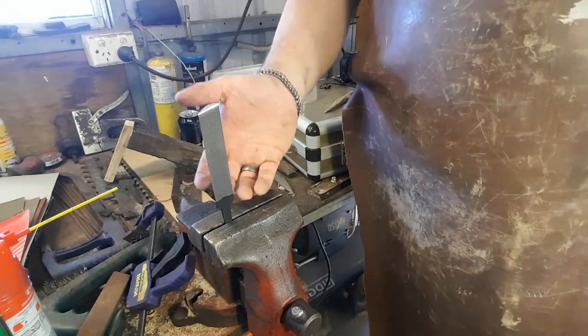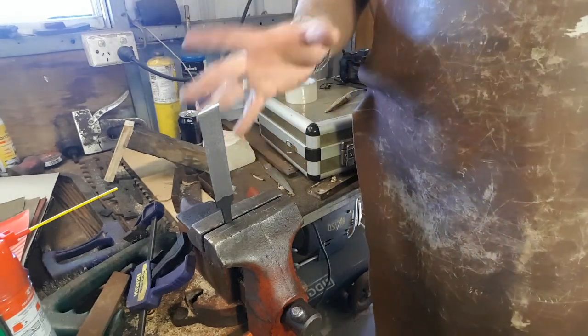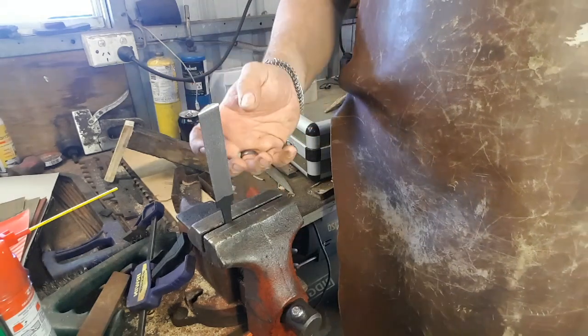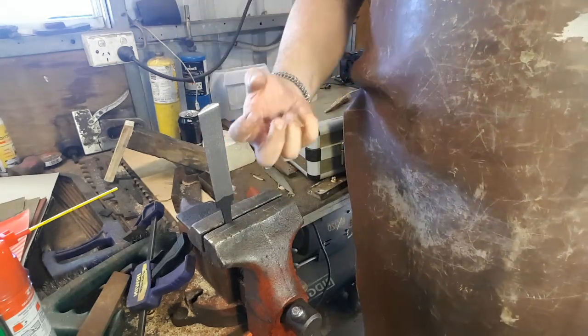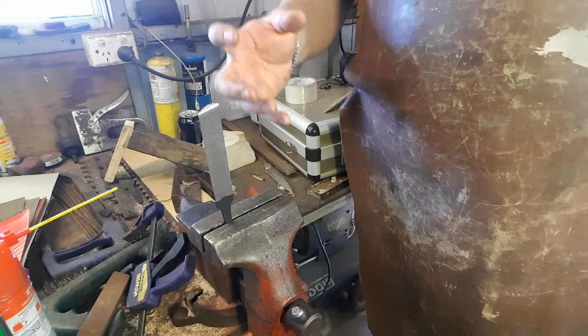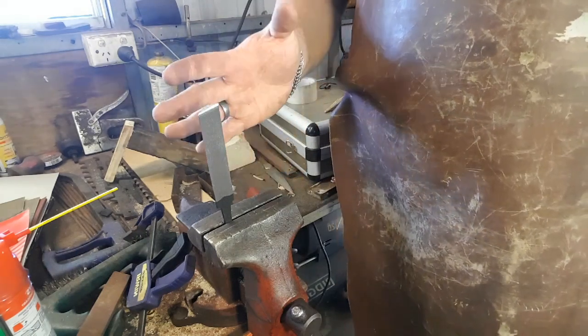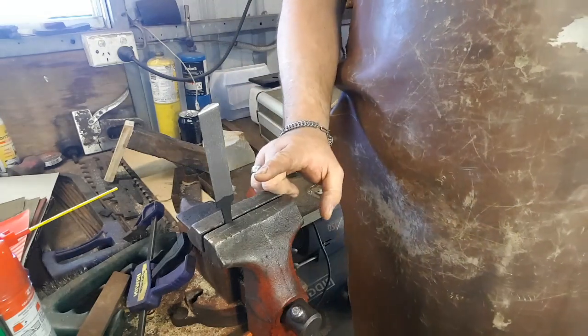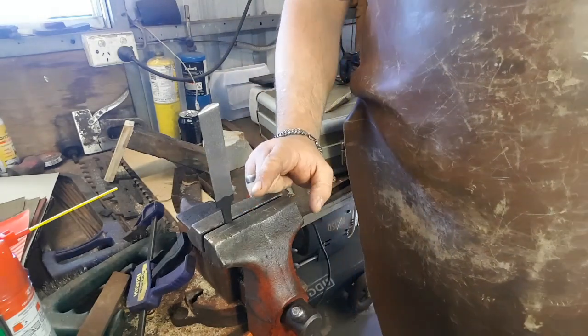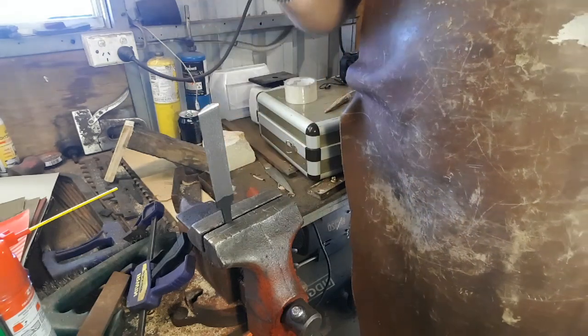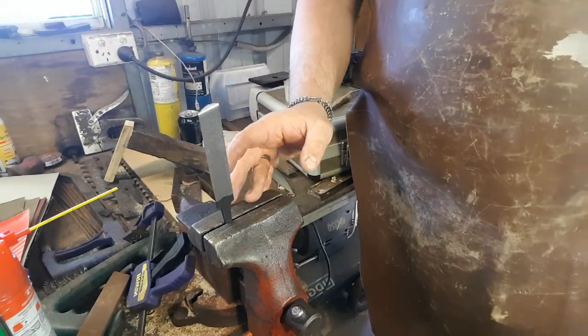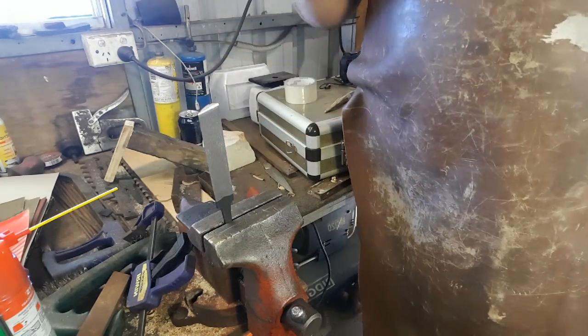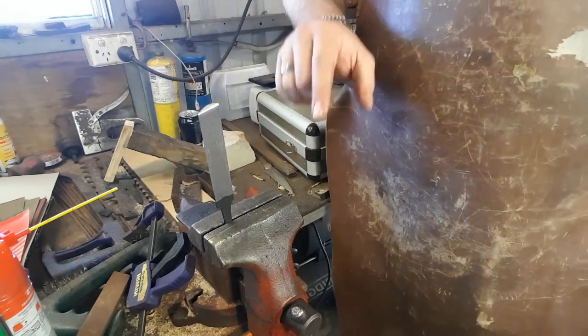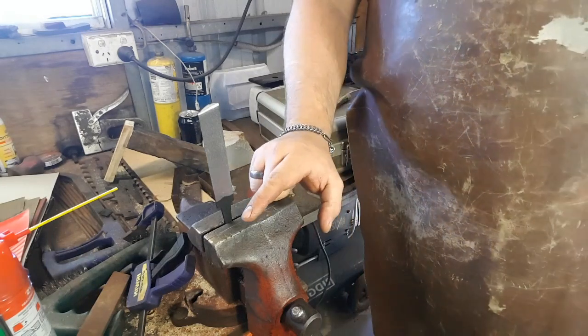But basically all we're trying to do is reheat this steel to a much lower temperature than critical temperature to bring back some of the toughness, the springiness of the steel, remove some of the hardness, but you get a much more usable piece. Now the important thing for this process is to have clean steel. Very clean, like acetone the surface. This has come straight off the grinder. I haven't touched the surface at all, but any oils, any fingerprints or anything like that will affect the color that the steel turns.